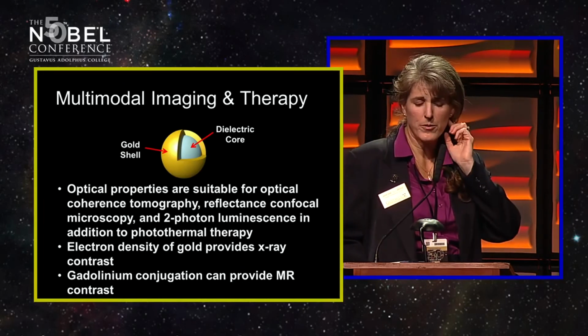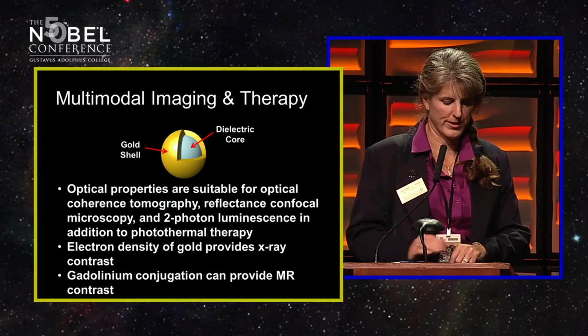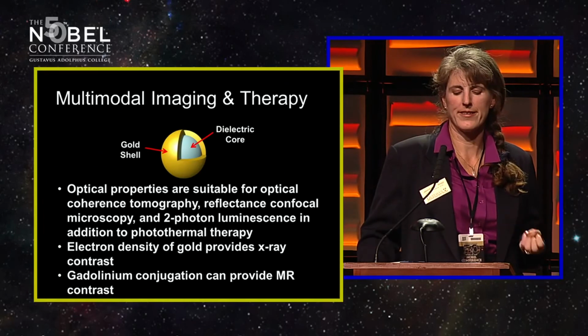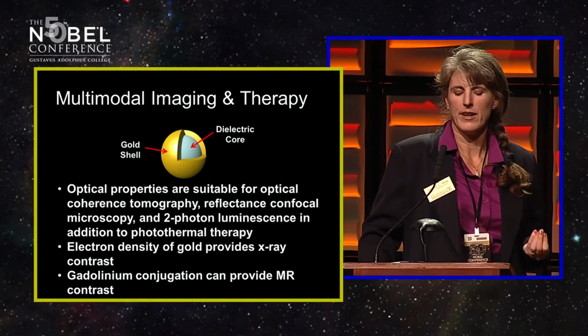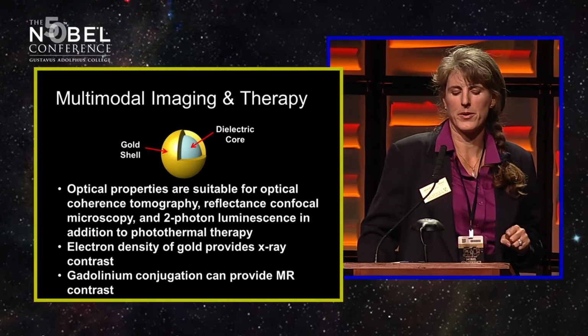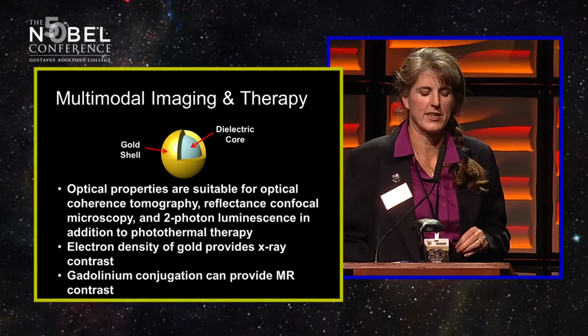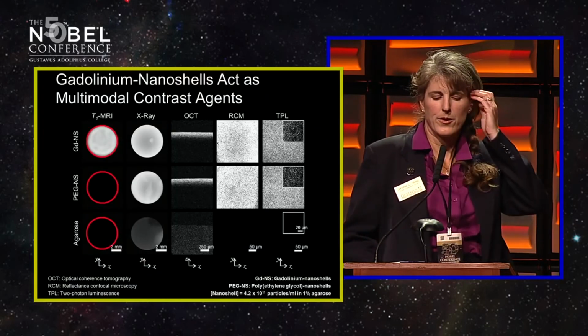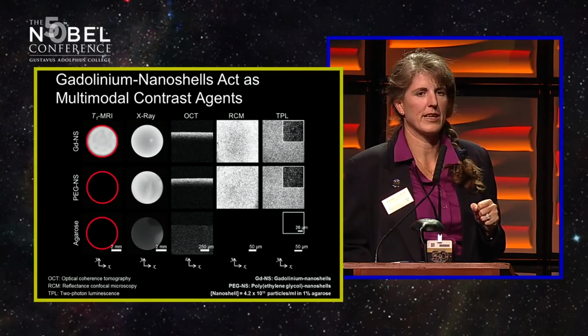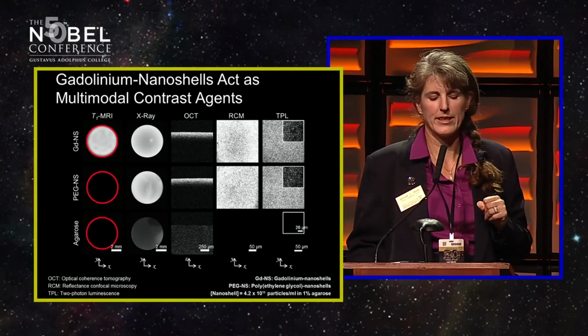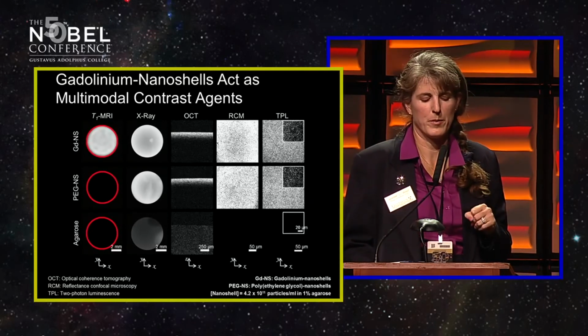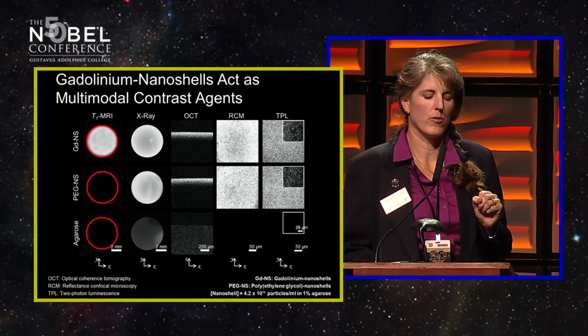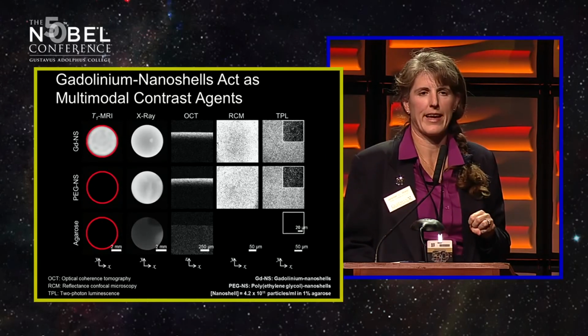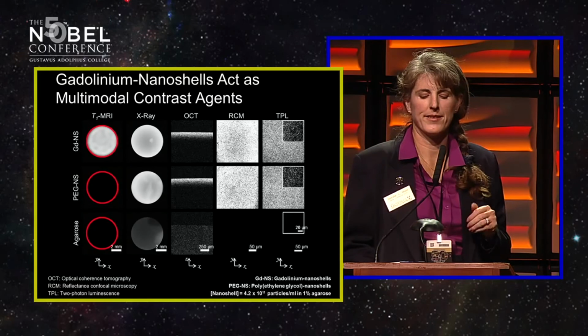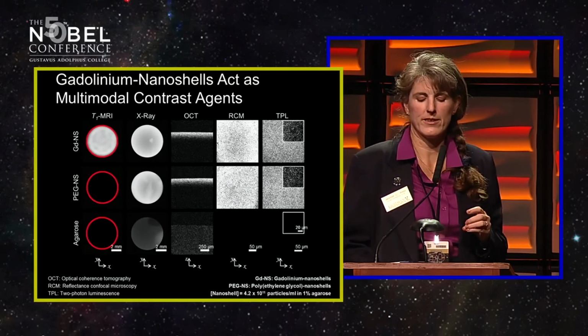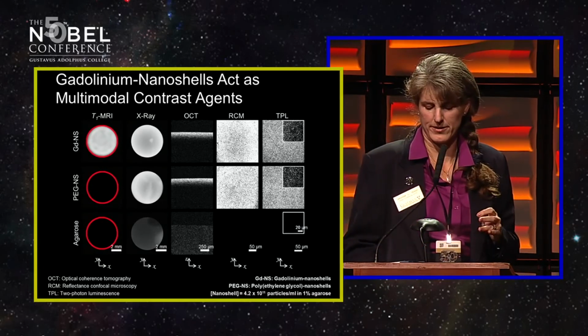And so we're looking at whether or not we can extend this to multimodal imaging, where in addition to optical imaging, you could also accomplish CT imaging, which you can get because the electron density of the gold allows for X-ray contrast. And then we've developed versions of these particles that incorporate gadolinium, which is an MR contrast agent, so that we can do MR imaging as well. And so if we look at images just of materials that have these nanoparticles embedded in them, we see the top row are the gadolinium nanoshells, the next row are regular nanoshells, and the bottom is just a pure control. So we see that we only get the MRI contrast, the first column, when we had the gadolinium incorporated. We get nice X-ray contrast in both cases. And then we have 3 different modes of optical imaging: OCT, reflectance confocal, and 2-photon luminescence, that all give us very nice signals as well.